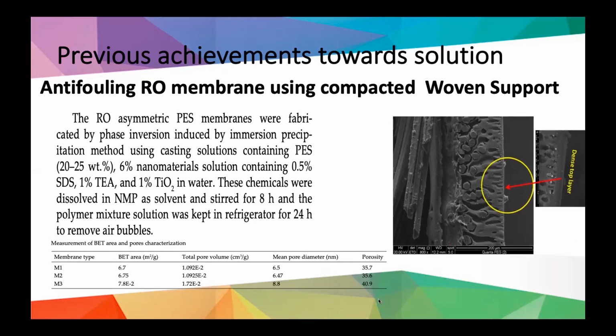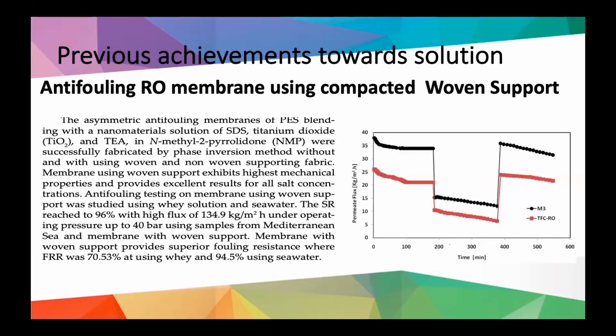Also, you can see here the change in the porosity. While casting on a glass plate, we get 35.7 porosity, which increases to around 40 and has a mean pore diameter of 8, when compared to the unsupported one, which is only 6.5. A great enhancement was found with the compacted woven support when using the fouling experiment, while using the woven support.